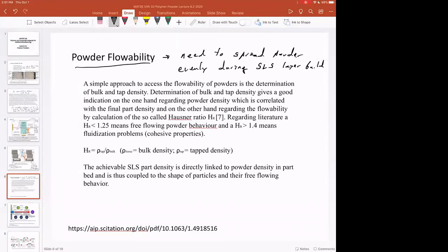And they use this cool parameter called the Hausner ratio. And all it is, what is the bulk density of the loose powder. So if you just take powder and measure its volume and mass, you can get a powder density versus this parameter called a tap density. And all the tap density is, you basically take a cylinder of a certain height and you tap it a certain number of times and you get this tap density. And so a Hausner ratio of greater than 1.4 means that you're going to have fluidization problems or the powder really likes to stick together, versus if you have a Hausner ratio of less than 1.25, you have this nice free-flowing powder behavior.